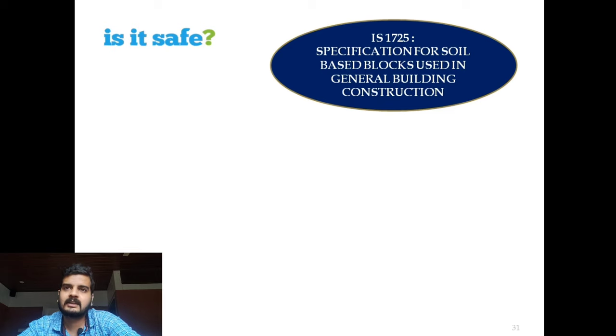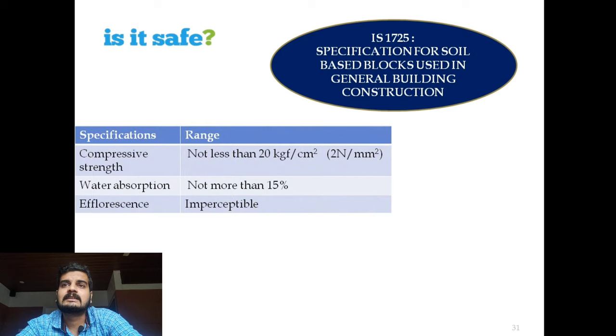For the interlocking brick, there is an Indian standard code book, IS 1725, specification for soil based blocks used in general building construction. Here there are some specifications, like the compressive strength of the brick should not be less than 20 kg per centimeter square, that means 2 newton per mm square. And the water absorption of the brick, if you keep the brick for 24 hours in water and compare with the previous weight, should not be greater than 15%. And the efflorescence, the attack by chemicals and all, should be imperceptible. These are the three conditions given in that code book, and these bricks are following it.